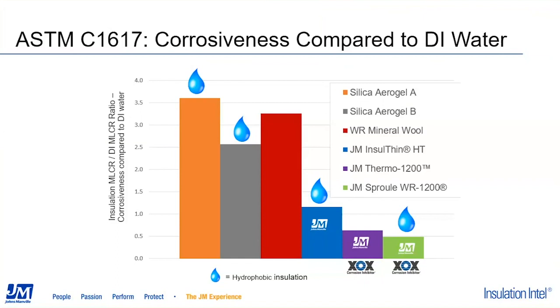If you look at the three bars on the left half of the chart, the orange, gray, and dark red bars representing the results for silica aerogel and water-resistant mineral wool products, you can see that they had a mass loss corrosion rate ratio between 2.5 and 3.5 times that of DI water, whereas the material represented by the blue bar in the middle of the graph, which is the Insul-Thin microporous thin blanket material, had a corrosion rate very similar to that of the DI water, and the Thermo 1200 calcium silicate and Sproule WR 1200 perlite products both had a mass loss corrosion rate ratio significantly less than that of the DI water. And as we'll demonstrate a little further in the discussion, that is a direct result of both of those products containing the XOX corrosion inhibitor.